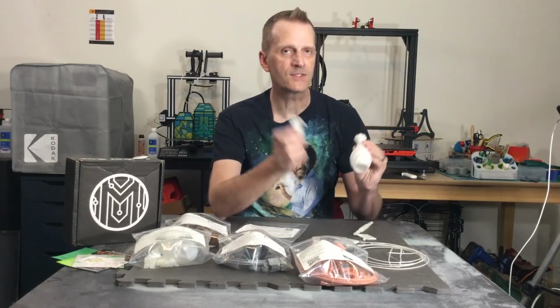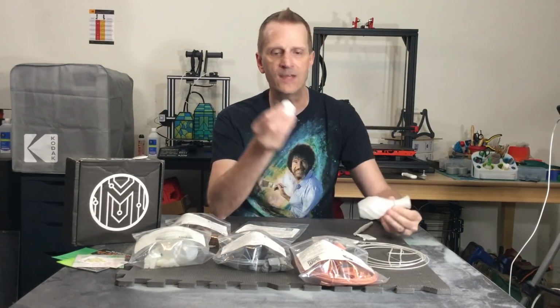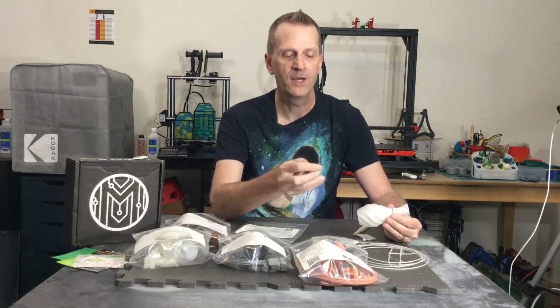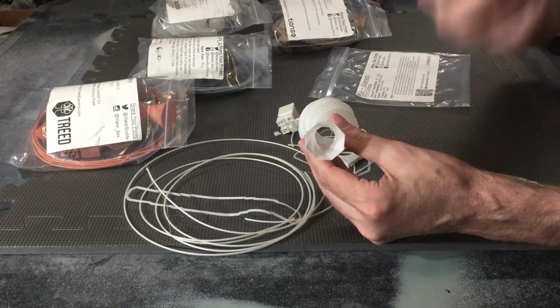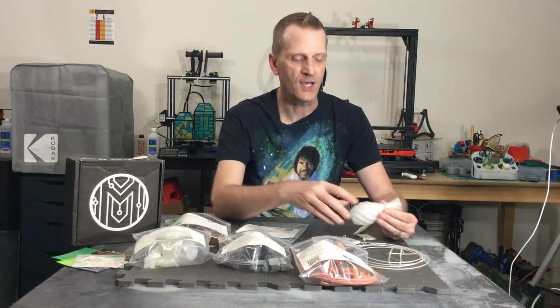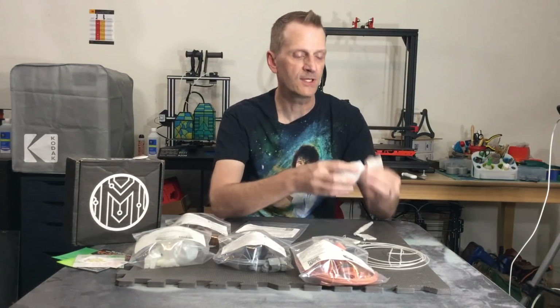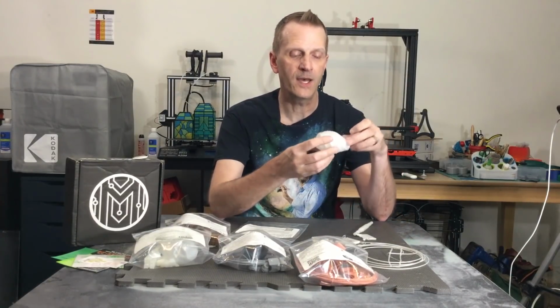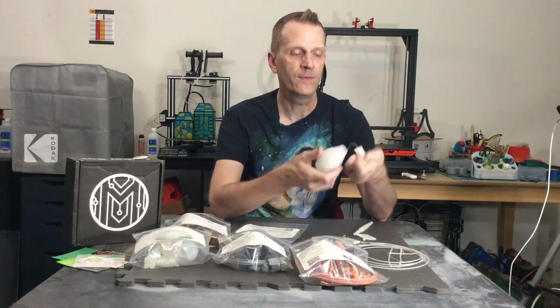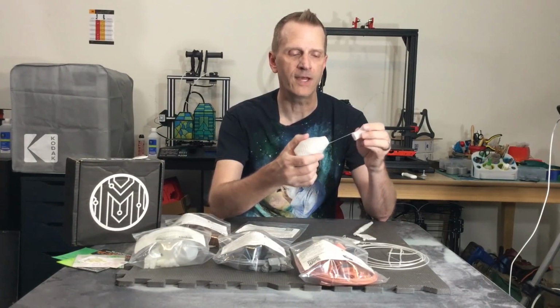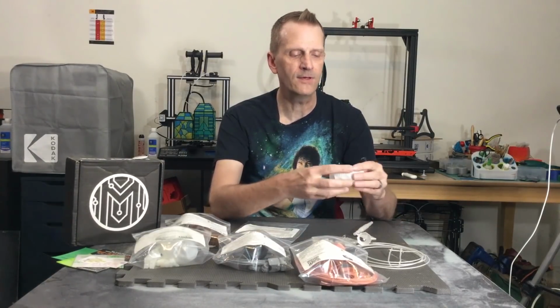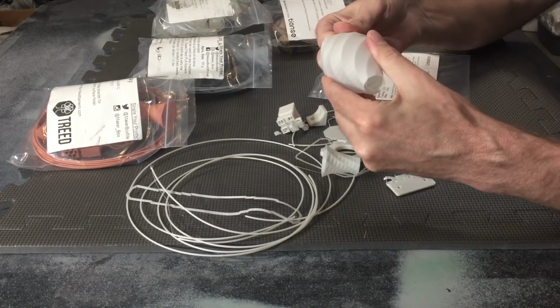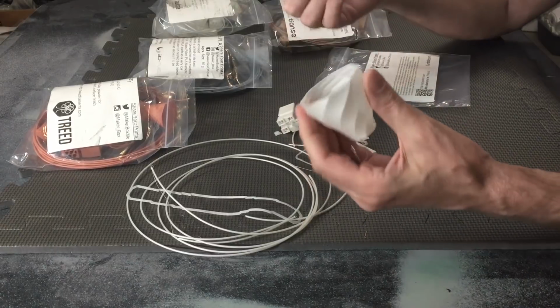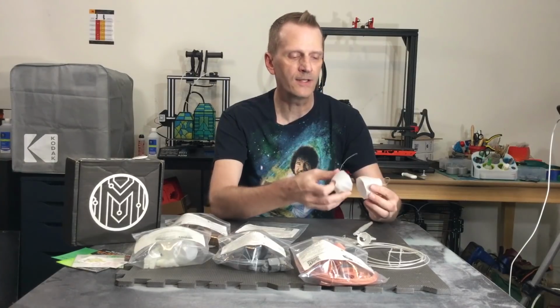So after the Cali Cat stuck so well, and after the Rose Twist Vase stuck so well and broke off at the bottom, and there's actually a piece of filament that stuck to the bed that required a little bit of effort, the acrylic, that's when I made the change. But for this particular print, when I pulled it off the print bed, not only did the bottom break, but the top part broke off, and it feels strong, but that gave me the indication. Well, yeah, there we go. And I didn't use any effort to do that. There's really not strong layer adhesion.